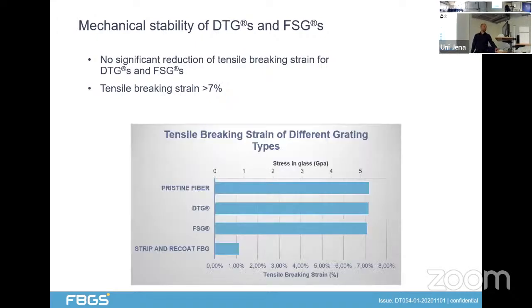If we compare these to a pristine fiber, so basically if we do destructive pulling tests on fiber, we see that pristine fiber has a tensile breaking strain of about 7%. And if you compare that with fibers with DTGs and FSGs inscribed, there is no significant difference. So the mechanical stability of the sensors is really high. And if you compare that to standard strip and recoat gratings, where we usually have a breaking strain of just 1%, this shows that these two techniques are capable of writing really mechanically stable gratings.